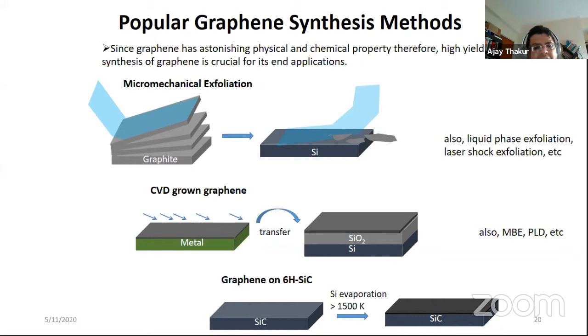Once you grow a monolayer of graphene on top of copper, and depending on requirement maybe bilayer or multilayer graphene, you spin coat a polymethyl methacrylate layer on top of it. So basically it is now a copper layer, on top of which there is a graphene layer, and on top of which there is a PMMA layer. Then one etches out the copper in iron chloride solution so that the entire copper is removed, and one is left with a lamella of graphene on top of the PMMA sheet. Then one takes this lamella and transfers it onto a silicon dioxide surface, and at the end the PMMA is washed away using a suitable solvent, typically acetone, so that the graphene is now coated on top of the silicon dioxide layer.